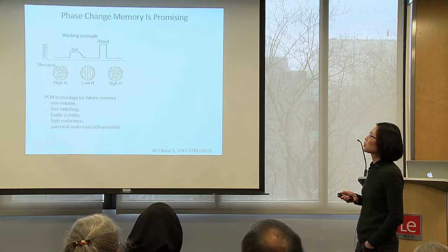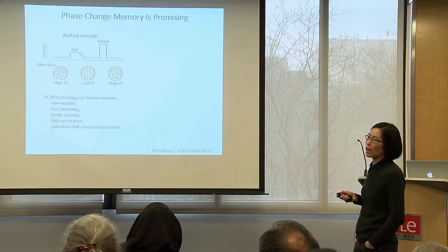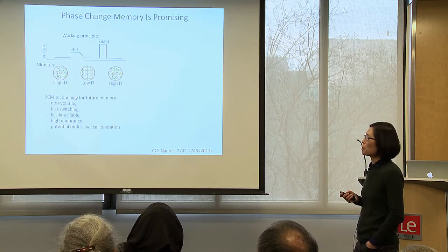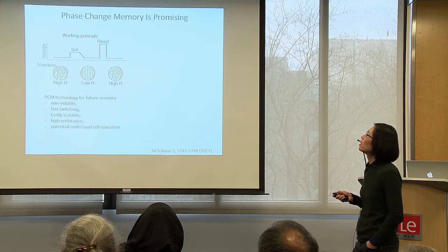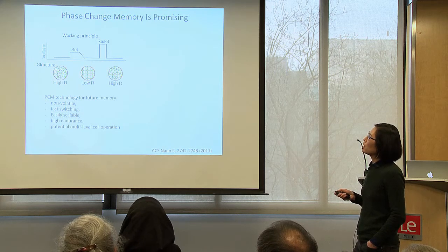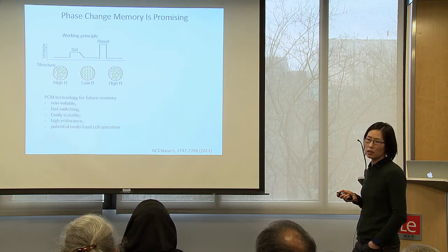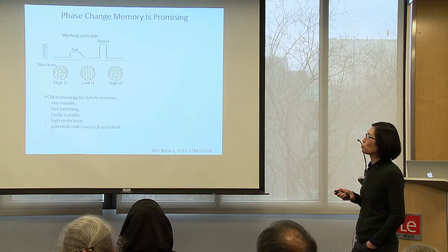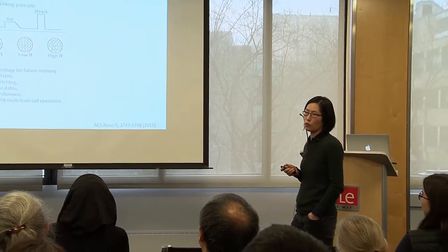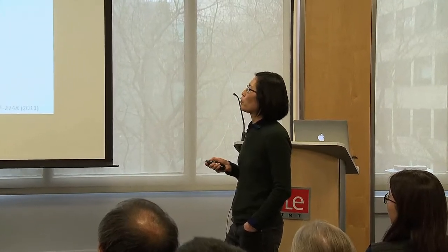The working principle of PCM is that it's a chalcogenide glass, usually some variant of germanium, antimony, and tellurium combined. You can very easily go from the amorphous to the crystalline state by a little bit of joule heating, using usually about nanosecond voltage pulses. In the amorphous state, the resistance is high. In the crystalline state, the resistance is low. So here is your bit. Okay? It's non-volatile because your information is stored in the crystal structure. So even if the power is off, the crystal structure remains.